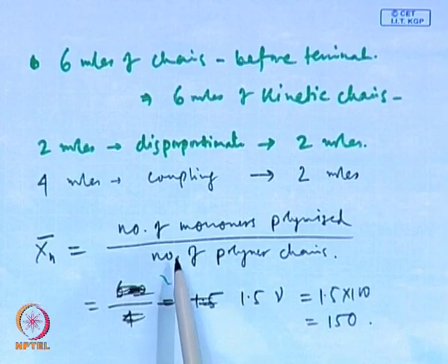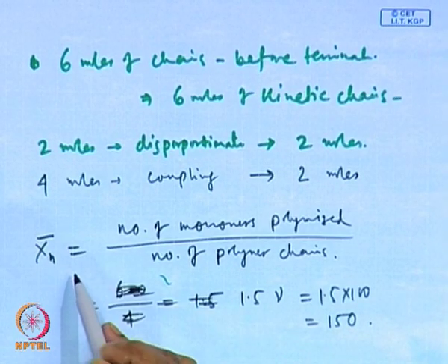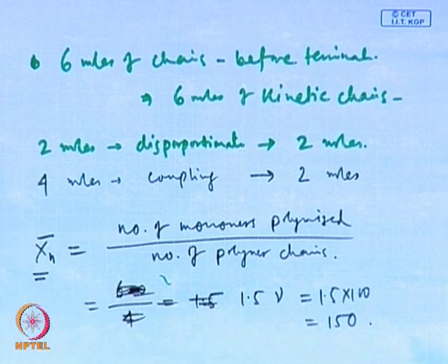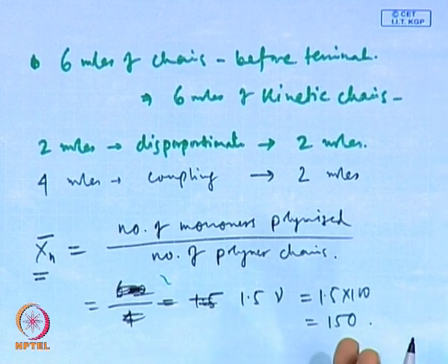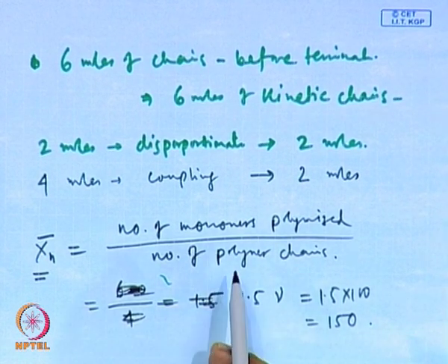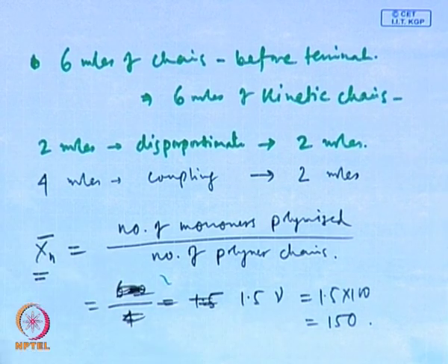Okay. So, that is the one fundamental difference between chain polymers and step polymers. How do we calculate, or understand what the average degree of polymerization means, or the average molecular weight? In the chain case, we do not consider the monomers, whereas in the step polymer case, we consider every molecule present at the end of the reaction.